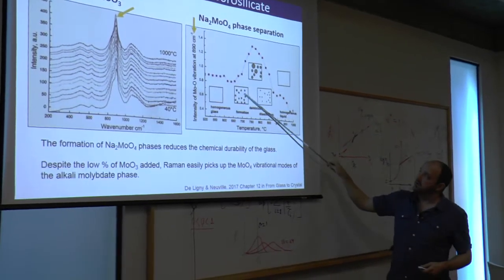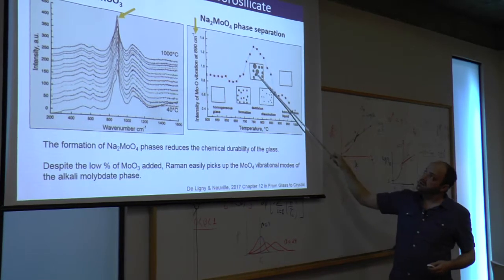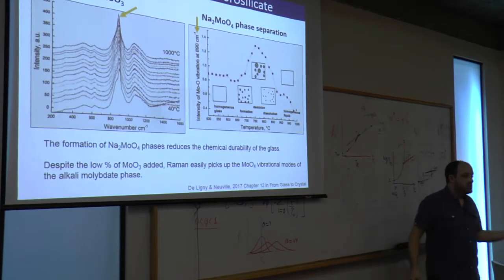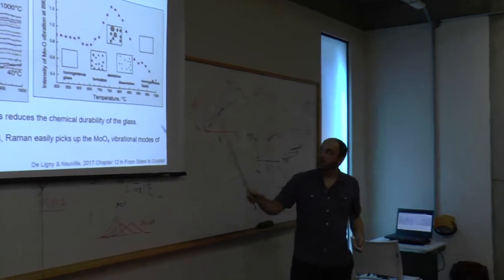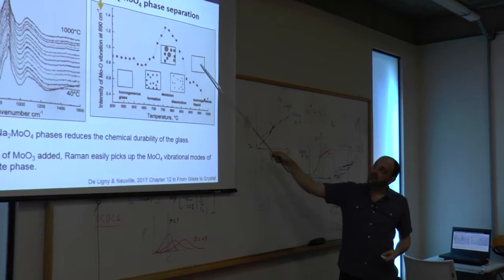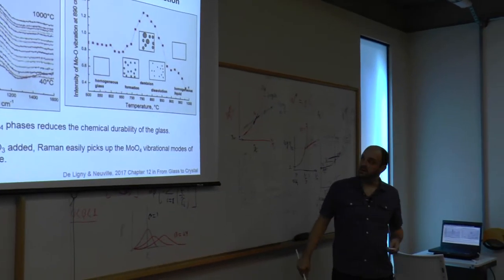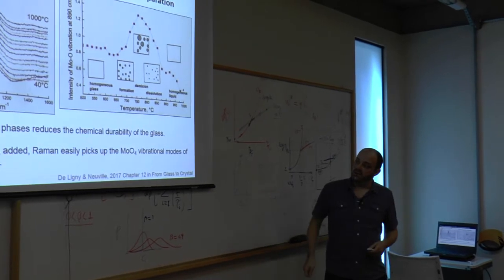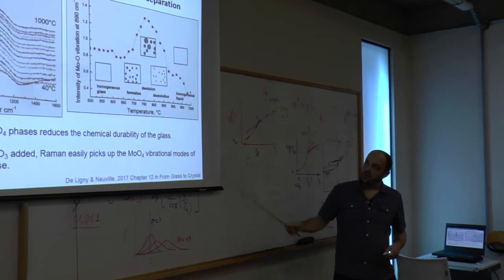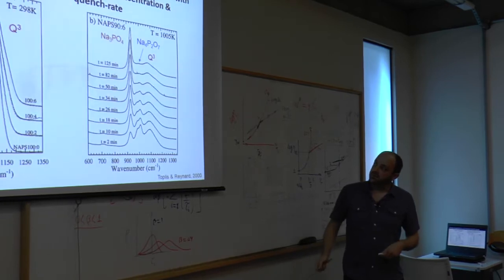And you get small amounts. At the maximum intensity, you have the most separation. And as you melt it, you re-homogenize the system and get rid of that sodium molybdate phase. And the intensity of the band follows that. So Raman is really nice for phase separation.